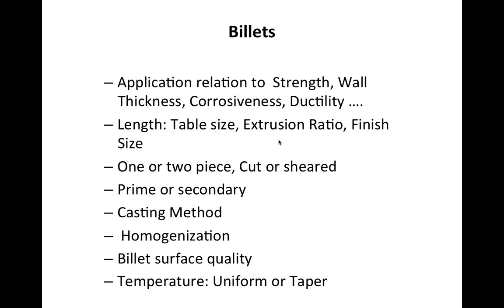The problem with sheared billet is typically there's deformation on both the front and the back of the billet, which affect mainly air entrapment once it's being upset. Also the use of one or two piece billets. Also whether the billet is primary or secondary. The casting method of the billet affects the amount of inverse segregation on the outside of the billet.